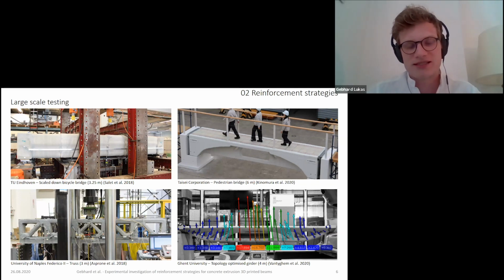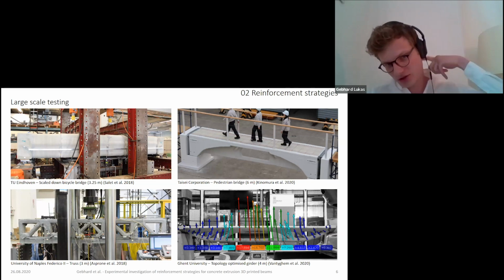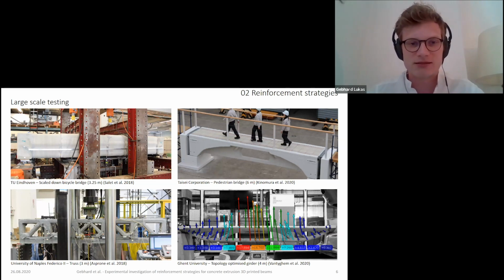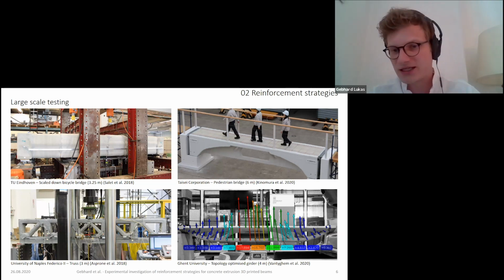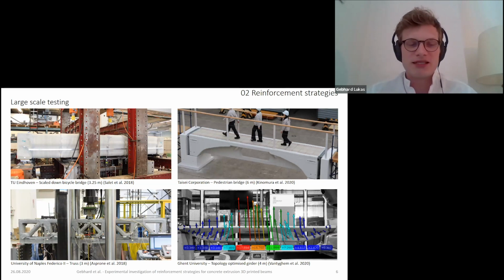So only a few tests have been performed on a large scale, and I want to introduce some of the tests here. So also this bicycle bridge at TU Eindhoven was tested in 4-point bending as a scaled down version. Also a pedestrian bridge by a company from Japan, Taisei Corporation, and a simplified version of the truss that we have already seen with external reinforcement was also tested in 3-point bending, and a topology optimized girder tested at Ghent University. And these tests have mainly been performed on really specific geometries for a specific use case. So it's hard to make general assessments from these tests.